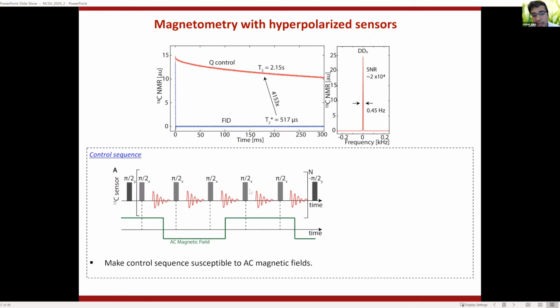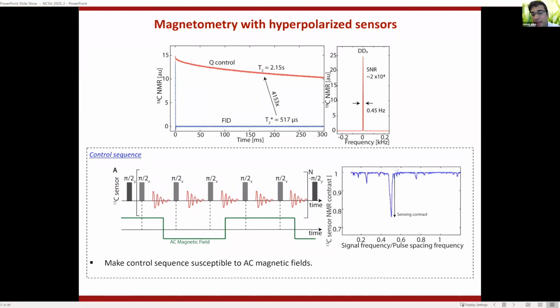It turns out if you write down the same sort of spin locking pulse sequence that we described before, this protects the spins against all interactions except magnetic fields which fluctuate at a very specific period. So this is not data, this is simulation, but it's basically the same idea. You can show that if the spins are subject to fluctuating magnetic fields of any origin, either artificially produced or through nuclear origin, or through electronic origin of this particular frequency, then the signal here will be reduced quite a lot. And the change in either coherence time or the signal can act as a proxy for you to detect these spins. And this is what we're working on.